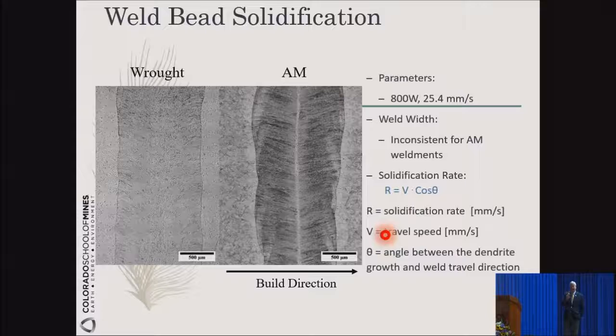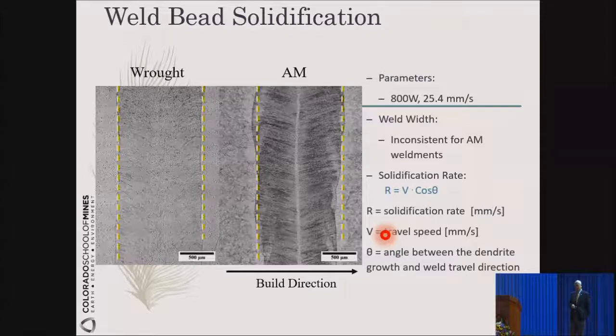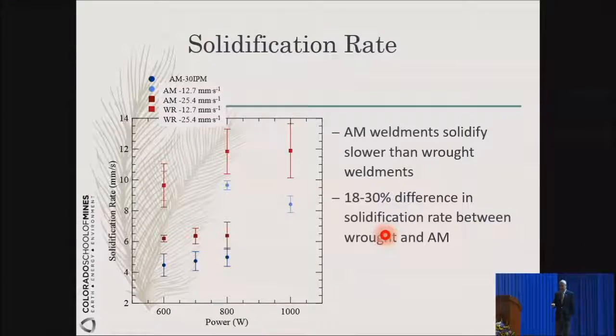Okay, so again, another difference yet. You look at welding on the wrought product, welding on the AM product. The fusion line, how uniform it is on the right-hand side here, and how rough it is on the left-hand side here. So AM does have this problem, in the sense that it does exhibit this heterogeneity. So you can calculate the solidification rate now. If you calculate it, you'll find out that AM actually has a lower solidification rate than the wrought material. Quite interestingly, why should that happen? That's again the question that we're pursuing.